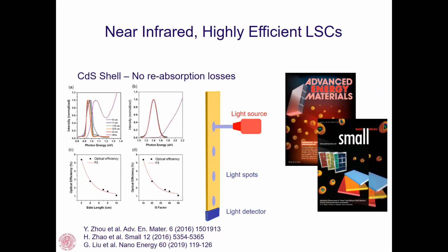And then once done this, we integrate them into solar concentrators based on polymethyl methacrylate. In the left panel, you see a non-core-shell system, and on the right side, a core-shell system, with photoluminescence spectra taken at different positions, so different distances from the light source to the light detector. And you see that in the case of the core-shell, we are able to remove completely the self-absorption processes and obtain the same shape of photoluminescence irrespective of the distance. So it means that your light is transmitted without being affected.